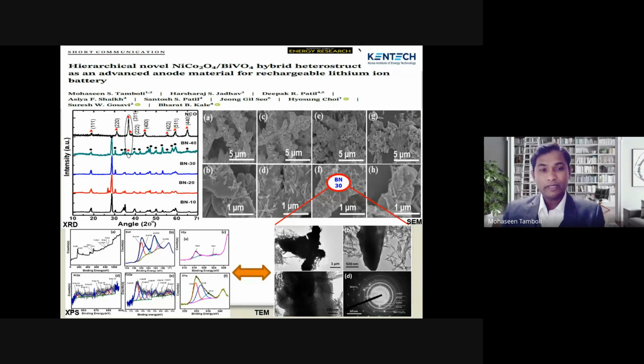With BiVO4, it's showing dendrite-like structures, and NiCo2O4 is showing a nanowire-like structure. So the nanowire structure is connected with the dendrite structure. You can see figures A and B, and C and D. There is the 20% BiVO4 and NiCo2O4 composite. Figures E and F show the 30% BiVO4 and NiCo2O4 composite. And figures G and H show the 40% NiCo2O4 and BiVO4 composite.